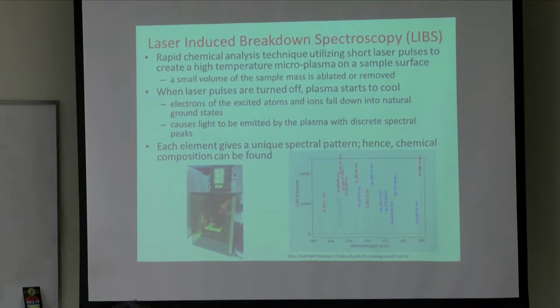But the whole purpose of it is a rapid chemical analysis technique, and it uses very rapid short laser pulses, and it creates a plasma on top of the surface of a material. And so you're actually damaging the surface of the sample while you're doing that, and that's what we call ablation, or laser ablation. This is when the laser damages the surface of a certain material. So the short laser pulses are hitting the surface of a sample, breaking it down, and you're creating a plasma.